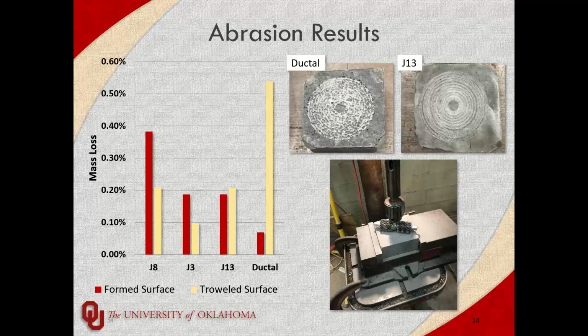But as you can see, on the form surface for the abrasion, our mass loss was much higher than Ductal. But J3 and J13 performed very similarly. It's probably because the slag cement tended to make up for the silica fume better than the VCAS did in J8.